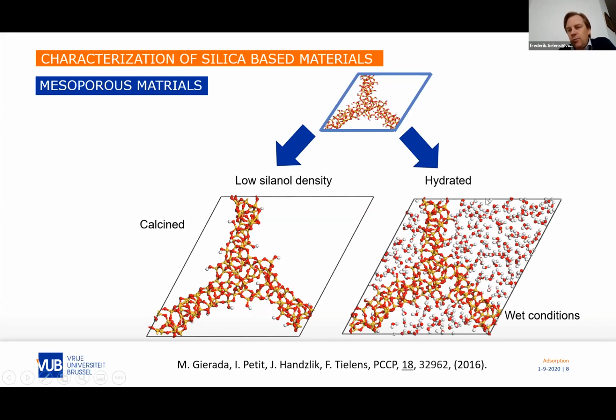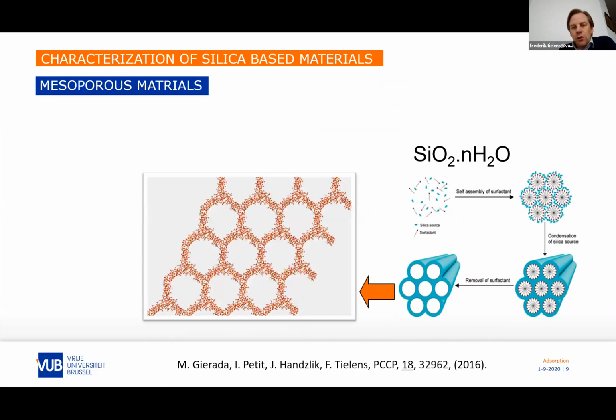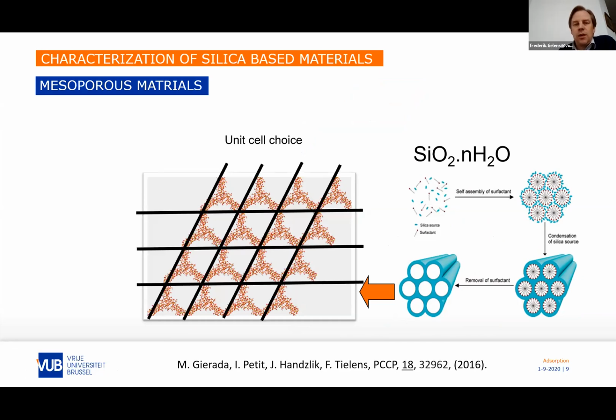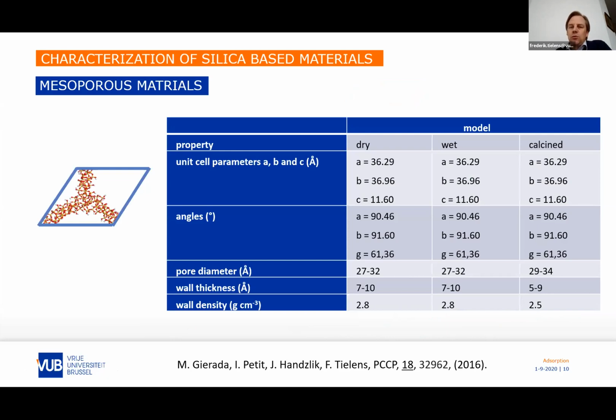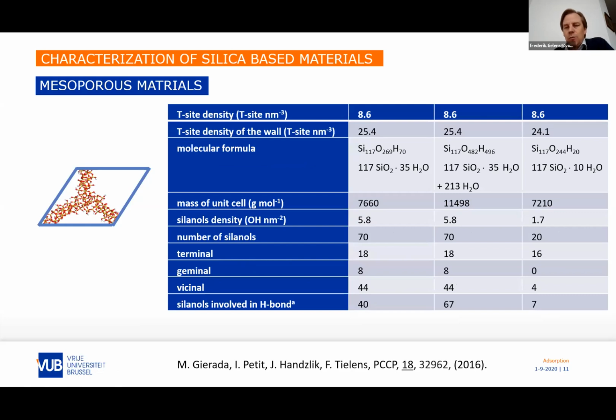Here you see that we filled the vacuum. What is the pore if you multiply the unit cell in 3D? So the interaction of water with our surface, and here we have the vacuum at a low hydroxyl density. This is how it looks when you multiply the unit cell. So we reproduce this hexagonal structure and these pores. Here you see again how the unit cells are organized. I don't want to go too much into details, but we can have some geometrical parameters for the different degrees of hydration of our model. These are different parameters that can directly be compared with the experiment. This was the aim, of course.